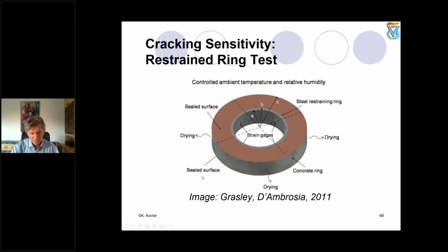You can see here, this was done by Grasley and D'Ambrosia, but in principle, this ring test has been known for years, maybe for 70 years, because the first publications are available from the 1950s in Portugal and some other countries. So this is a very important and very simple technique. We are casting our concrete around the rigid core, which is usually made of steel, a very stiff material. We can say this is stiffer by an infinite number of times than fresh concrete. We can neglect the modulus of elasticity of the fresh concrete.